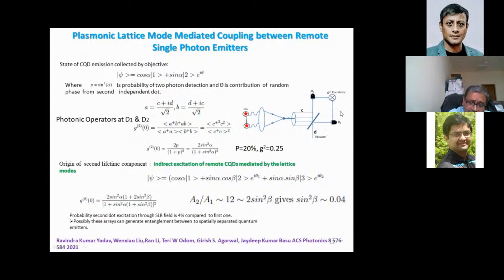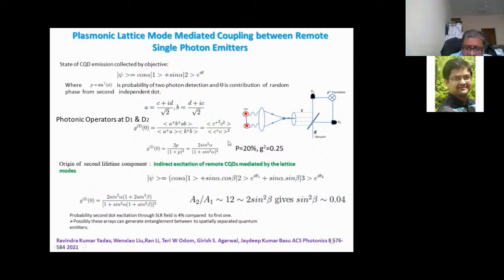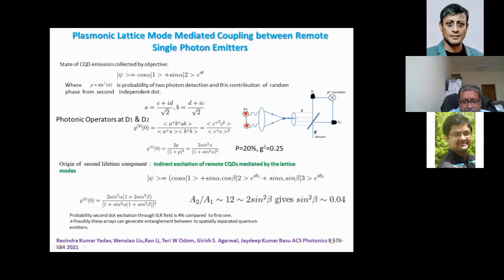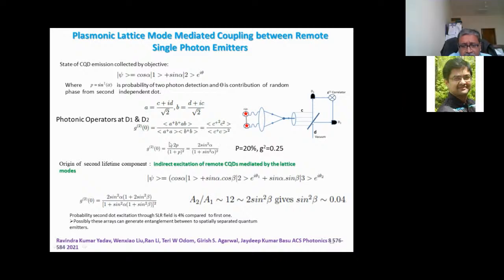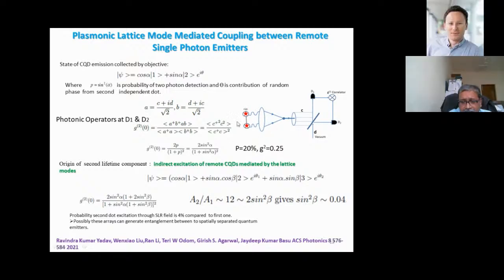So this is a typical G2 measurement. You have the two detectors, so the two photon detection probability can explain why this value is not zero. This is not present on glass, but it's something that we seem to pick up, and this could be related to the fact that you have this extended mode, the surface lattice resonance mode. At this point we do not have the detailed model or understanding of what exactly causes it, but at least this is a possible way to look at it. So there is a 20% probability, to cut a long story short, of having one more quantum dot's signal being detected, and that can give rise to this behavior.